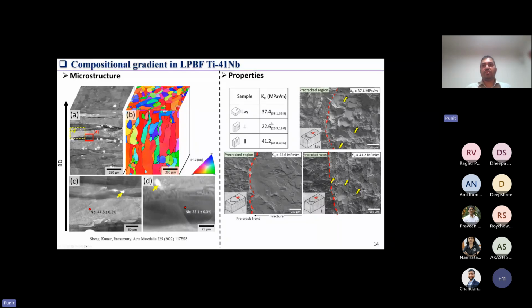And looking at the fracture surface, we see that in the case where the crack path does not interact with these niobium poor regions, you can see a lot of flat cleavage fracture surface, and that is why the fracture resistance is much lower. In the other two directions, this is how the niobium poor region is oriented, and you can see when the crack goes through these regions, you have some plasticity. Again, here you can see the same thing, where these are the lines of niobium poor regions, and you can see plasticity in those regions. So that is what explains the significant difference in the fracture resistance of this material.